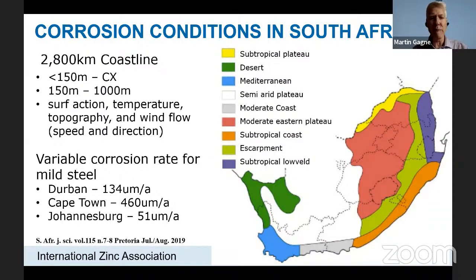If we go from 150 meters to a kilometer inland, the corrosivity will depend on the surf action, the temperature, topography, and wind flow, and we can see variations in corrosion rate. One thing that was interesting here is that we have different corrosive environments along the coast of South Africa. If we start on the east, it's a subtropical coast. Then in the south, we have what's labeled in this report as a moderate coast. And then on the west side, the Mediterranean, which I found interesting.